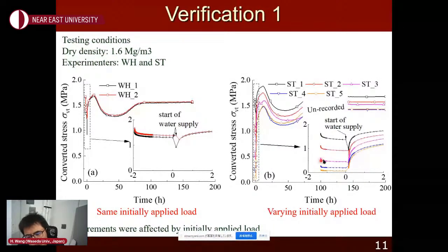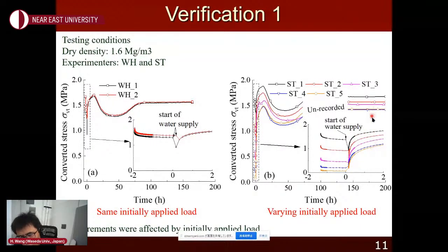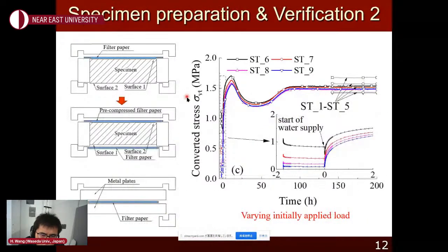However, when we change the initially applied load, it can be seen the measured swelling pressure also changes somehow. The larger the initial pressure we applied, the larger the final swelling pressure we measured. So here's a problem. The problem is induced mainly because of the initial pressure applied to the specimen. Sorry, it's a little bit complicated to explain here, but we found a way to solve it.